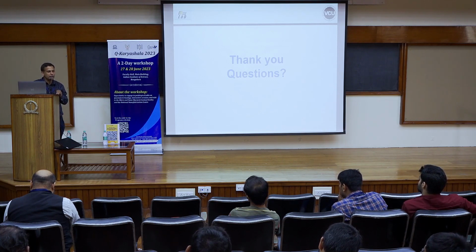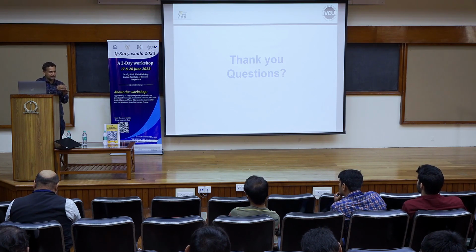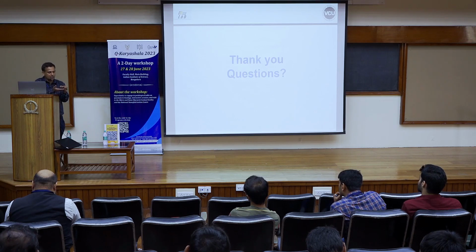And the solution to that, the skyrmion demonstrated on the film, is very much at the level of physics, where we understand what's going on. But if you have a stack and you only change the heavy metal layer, and the CoFeB is the same CoFeB that you can use to create a skyrmion, that's the same thing used in a magnetic tunnel junction. If you can engineer the heavy metal layer, which you anyway need for a contact, with some interface, and this works, you can switch from up to down with better error rates. Then you already have all the structure to try it out.